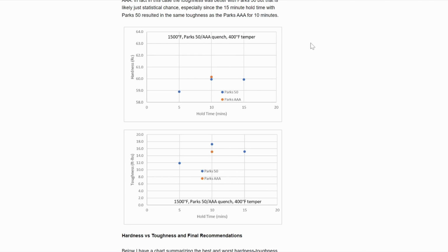Another reason to avoid very short austenitizing times, this is a study we did on 8670. When we held for 5 minutes, we got 59 Rockwell and 12 foot-pounds. But when we held for 10 to 15 minutes, we got 60 Rockwell and 15 foot-pounds.